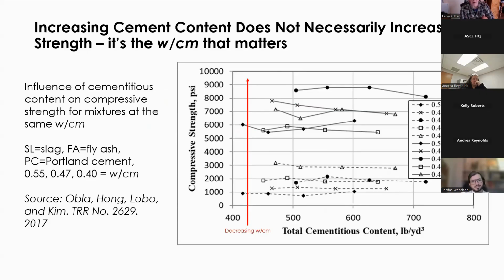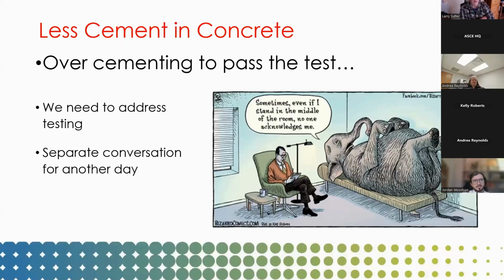Next slide. And if you look at this idea, this plot here is just done from National Ready Mixed Concrete Association. Each of these lines on a plot is showing a constant water to cement ratio, but then increasing the cement content to get there. And you can see as we change the cement content, we really don't see much change in strength. What we really want to do is change the water to cement ratio. So we can get there without changing the cement. And of course, the big thing that we never talk about is testing, over cementing to pass the test. And in the interest of time, we'll come back to that some other time.